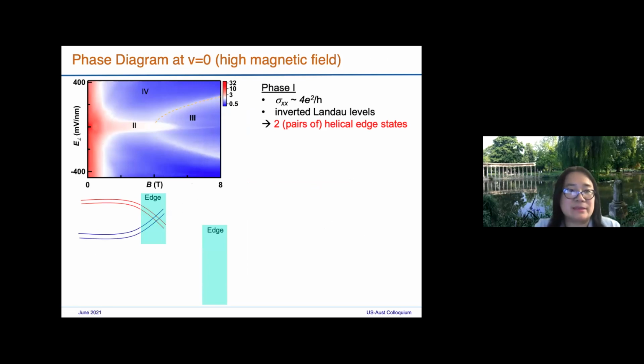Each of these bands is spin degenerate, and so the hole-like band will disperse down and the electron-like band will disperse up. They cross at the edge, and so this will give us basically 4 times the conductance quantum.